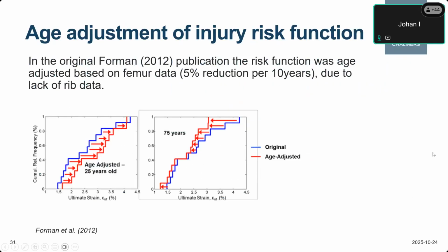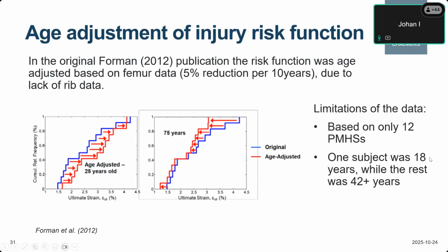So in the original Forman 2012 publication, the risk function was age adjusted based on femur data, because we didn't really have a lot of rib data. In that case, the femur data showed a 5% reduction of strength per 10 years. The big limitation at this point was that we only had data from 12 cadavers. And actually, those are the 12 steps that you can see in this empirical function. Those represent the change in risk for these 12 cadavers.